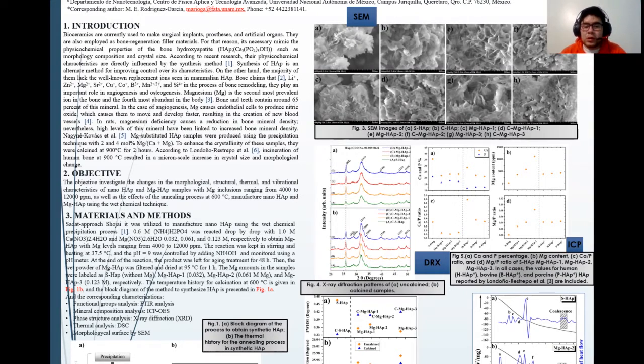Figure 3 A, C, E, and G show the SEM of the calcium hydroxyapatites that exhibit high-density flower-like structures, which disappear after calcination at 600 degrees Celsius. This is in figure 3B, D, F, and H. The presence of the flakes is due to the reaction byproducts that were removed by calcination. Londoño Restrepo reported that during the calcination of hydroxyapatite at 400 to 900 degrees Celsius, the crystal size increased from nano to micro. However, before the transition occurred, a coalescence phenomenon happened when crystals were still nanometric.